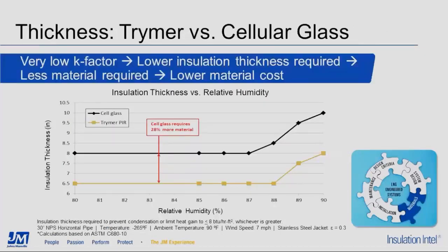The lower thermal conductivity of PIR leads to a lower insulation thickness being required compared to cellular glass. This in turn leads to less material being required for PIR, which yields lower material costs. The graph on this slide shows an example of the thickness of PIR and cell glass needed for a typical LNG scenario at various levels of relative humidity. Of course, as the relative humidity increases, the thickness required for both materials increases, and this increase begins at about 87 to 88% relative humidity, as you can see in the graph.